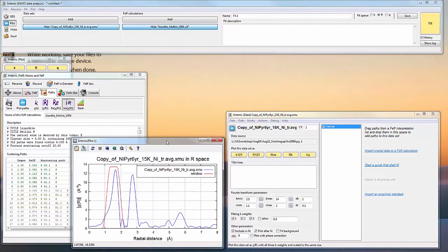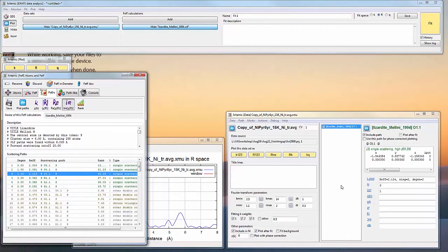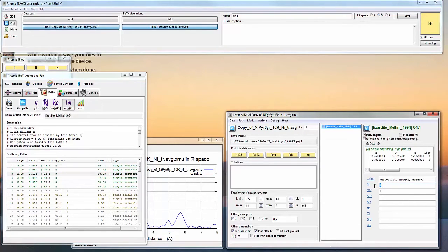So now we have our list of atoms and the scattering path, and we're going to select our first shell, which is our oxygen shell, 1.65 plus about 0.4 is 2.05. This is our first one here, and you can see the degeneracy is a little bit different here. It's not 6. That's because there's a little bit of distortion in the octahedron. So I'm just going to pick one of these paths and assign them all to be 6, because that's what...